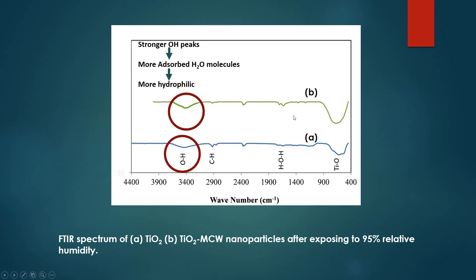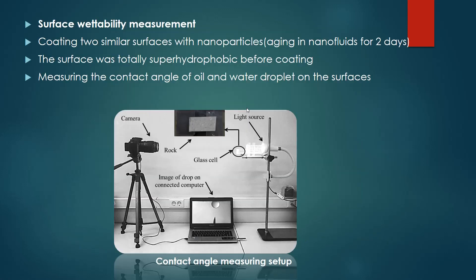So, according to this picture, TiO2 microwave nanoparticles are more hydrophilic than TiO2. Second, surface wettability measurement: coating similar surfaces with nanoparticles, aging in nanofluids for two days. The surface was totally super hydrophobic before coating, and we measured the contact angle of normal heptane as oil and water droplets on the surfaces.